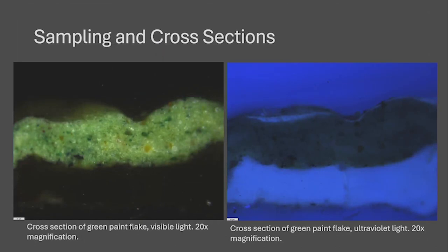Now, this is what I meant to discuss. To further identify the materials that were used by the artist and how she applied them, we took a number of samples. This is one of the samples that we took from a discrete area of damage in the green background. There's a mixture of different pigments in the sample, all mixed into one paint layer. And this is consistent along the samples that we took. It seems to be Covington's main method of painting directly with paint mixes rather than with glazes. The only time that she appears to use multiple layers is for discrete details like the straw, where the elements need to stand out.